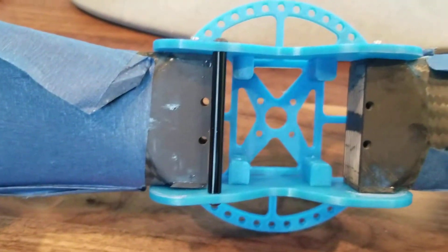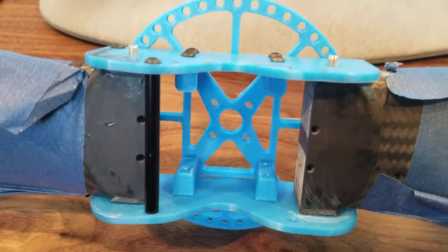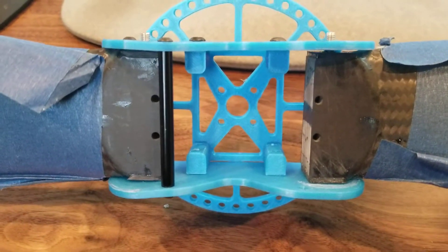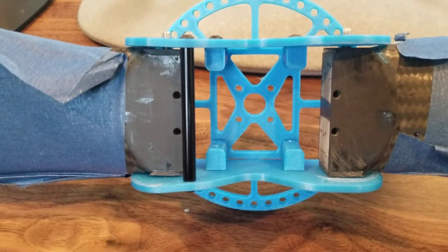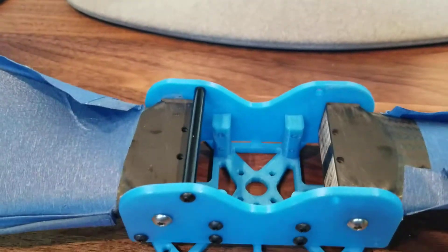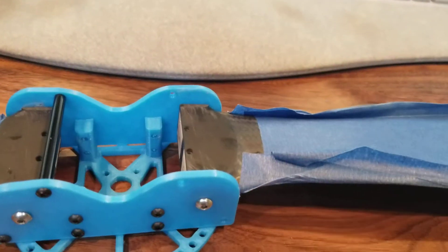What I'm going to do is cover the end piece with carbon fiber. I made a mold that I 3D printed out of PVA, so it'll dissolve in water so that I can just put it in with the carbon fiber, clamp it down, get all the excess out and really strengthen this piece up, so that the bolt holding it in won't slide through under load.